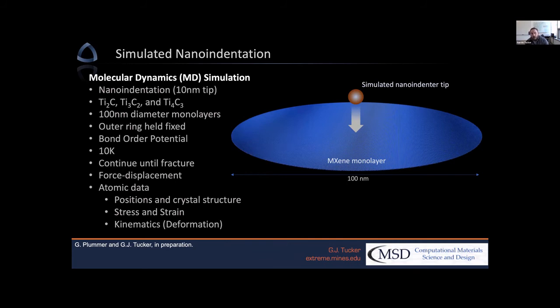And like I said before, the limitation was computational efficiency with the reaction force field potential, because we can only get to a certain size. And now we can get into the hundreds of nanometer size and very much approaching what is experimentally done as well. And so we did this for all three of our titanium carbide systems.